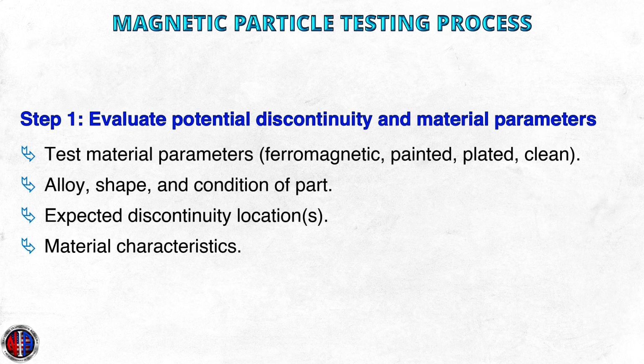Alloy, shape, and condition of the part. Will the material composition, geometry, and/or surface conditions impact the testing results? Rougher surfaces can result in particle accumulation, causing false indications, which can cause confusion during the evaluation process. The general rule is that the smoother the surface, the better the evaluation.